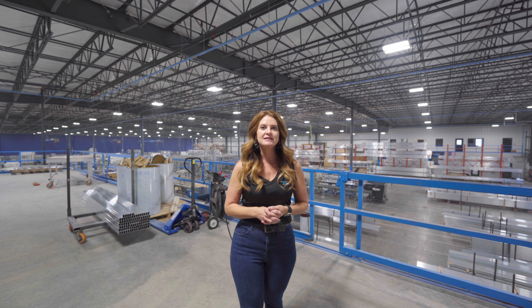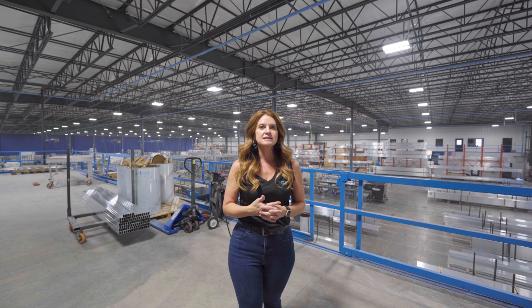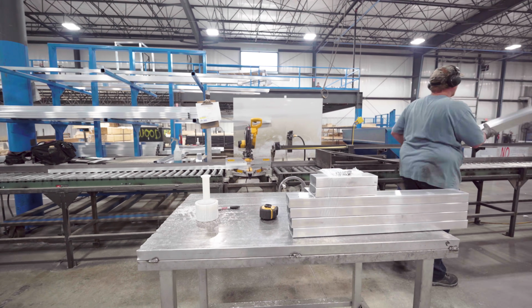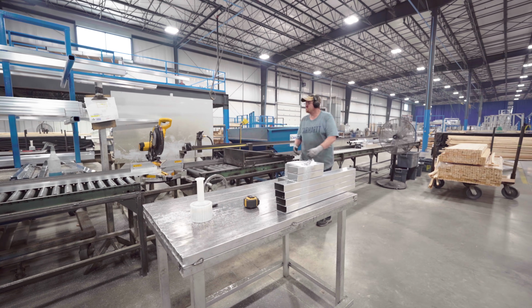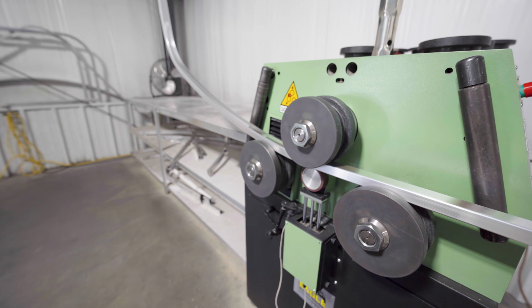We're pretty unique in the industry in that we're one of the only manufacturers to use the dyne test on all bundles of aluminum before we use them. The dyne test allows us to make sure that we have the best level of surface energy, which then allows us to have the highest level of adhesion in the lamination process. Each saw cuts directly from the engineering drawing, so there's less room for error. All radius profiles are done in-house on our CNC bender.